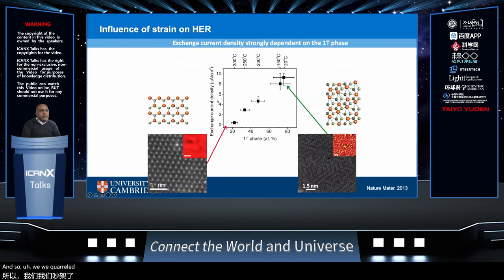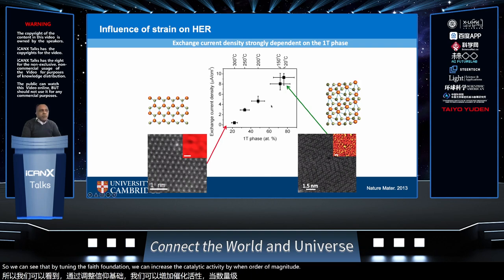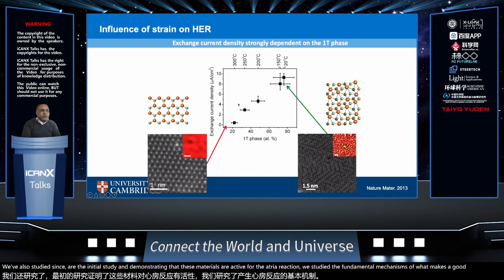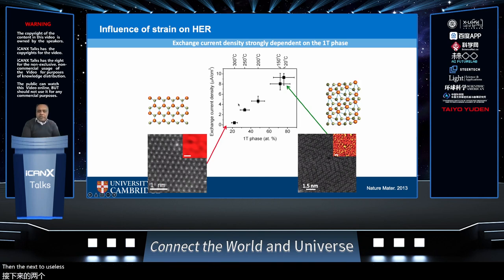And so we correlated the catalytic activity by plotting the exchange current density. This is the exchange current that takes place at zero volt as a function of the 1T phase concentration. So we can see that by tuning the phase concentration, we can increase the catalytic activity by an order of magnitude. Since our initial study demonstrating that these materials are active for the HER reaction, we studied the fundamental mechanisms of what makes a good HER catalyst. So in the next few slides, I'll take you through those basic results.